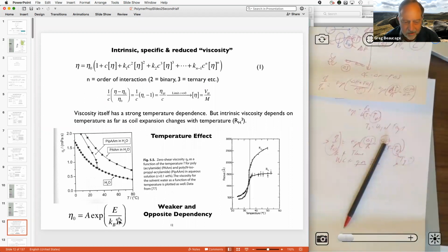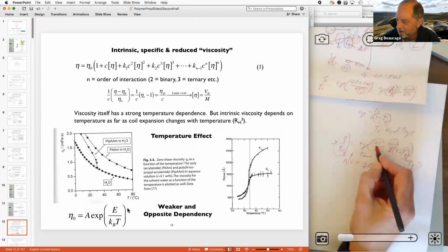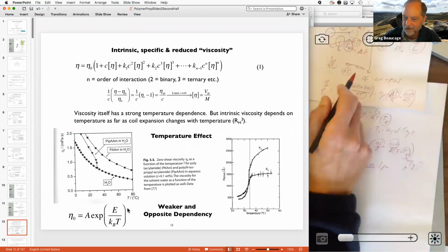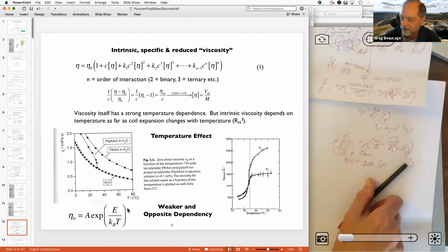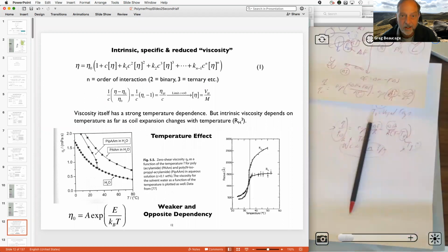Near the glass transition, you have one parameter, the Vogel temperature. And if you find out that doesn't work good enough for you, you can add another parameter, which is this entropy. And again, the entropy change probably changes with the shear rate, so you have to really specify the shear rate for this thing to work. Generally there's a WLF equation for polymers that people talk about, which I don't remember offhand, but I can find it in a second.